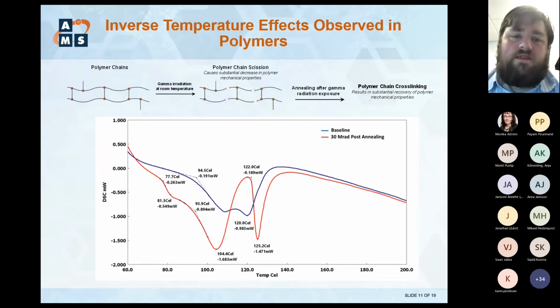But in our process, once you heat it up and go through an annealing process, essentially a thermal annealing process, you get cross-linking. You do have to do that in oxygen. You can't do that in a nitrogen environment. The cross-linking you see is driven by oxygen being available for the material, so the recovery you're going to get. So what happens is the chain scissioning induces severe decreases in mechanical properties, tensile elongation properties, essentially decreases the toughness of the material, but the cross-linking actually recovers a lot of those mechanical properties over time.